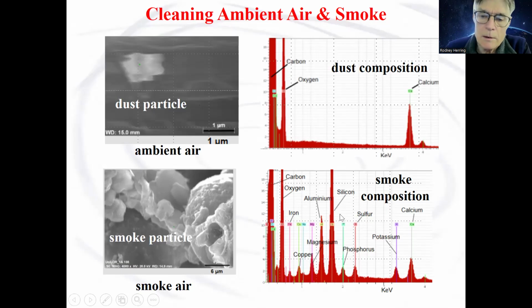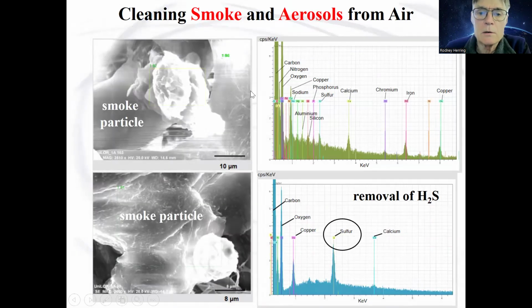And we can measure the composition of these particles. Additionally, here we have a smoke particle, and you can see that there's lots of nasty things in that smoke particle. So it's nice that they're being removed. Here's a smoke particle with a high sulfur content. So it's, as we know, there's a lot of sulfur, H2S in smoke. So it's being removed. And the reservoir, if we have lots of H2S, we can see that it's turning acidic.